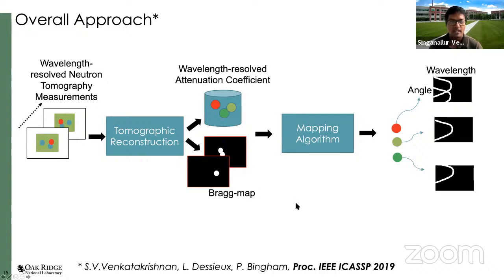So in order to get around this, we've developed a framework which first involves doing a tomographic reconstruction. But the reconstruction is done so that we are able to not just do a reconstruction, but also identify measurements which were impacted by this Bragg scatter. And once we do that, we can do something more. We can relate each of the domains in the 3D object and say when it went into the Bragg condition. So you get this binary indicator using this proposed approach.